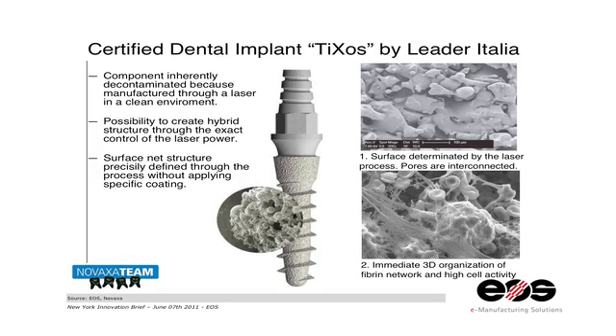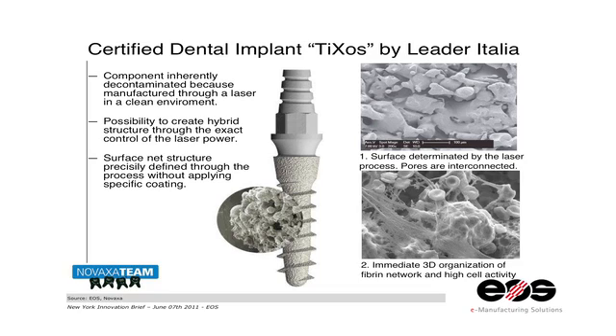Again dental, moving a little into the implant market. One of our customers in Italy is producing the Tixos implant by Leader Italia — and they've already announced that implant here in the US, getting a 510(k) for it. This implant has a very interesting design: usually dental screws are highly polished shiny parts, but this one has a very rough surface, using the benefit of the technology, because by sintering the parts we provide a rough surface. With this rough surface, you get very good osteointegration of the part. Again, I hope you don't need it.